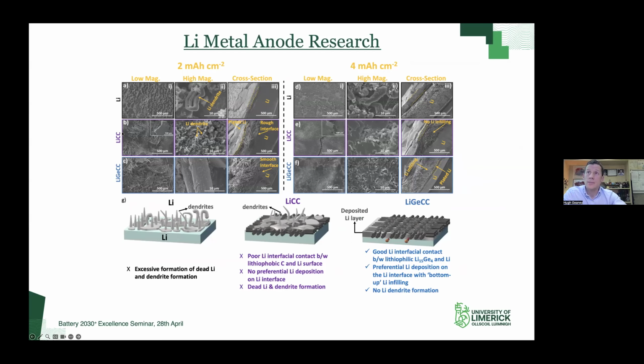For the lithium current collector one, where it didn't have the germanium incorporated, these are top-down images that are shown here. And what you can see is even at 2 milliamp hour per centimeter squared, you have significant lithium deposits on top of that layer. Okay, so this is shown down here schematically as well. So we don't have preferential lithium plating underneath the layer. And these are shown from the cross sections as well. So at the 2 milliamp hour per centimeter squared, shown here with these dotted lines. And similarly here for 4, you have no lithium infilling throughout that carbon cloth here. All of the lithium is occurring on top of the layer.